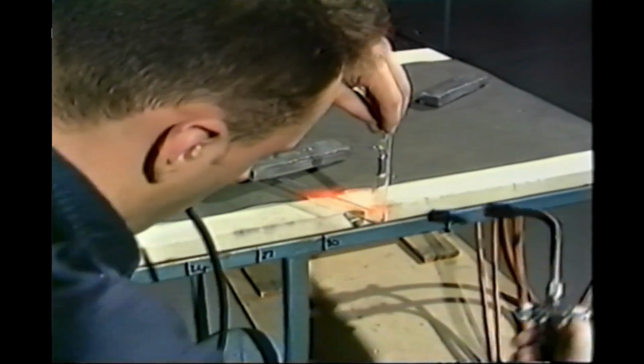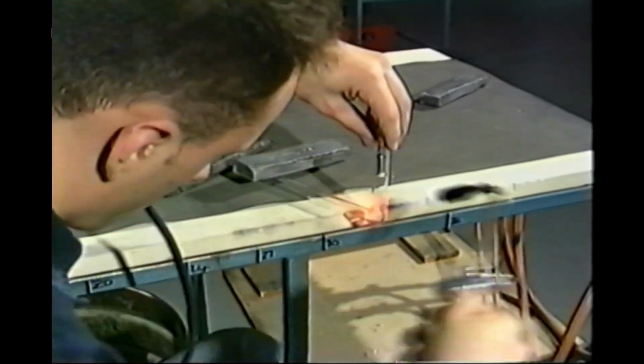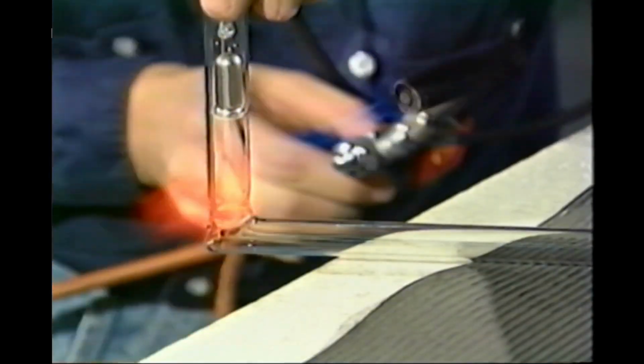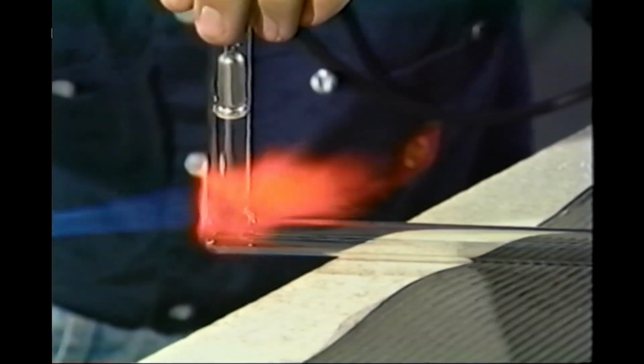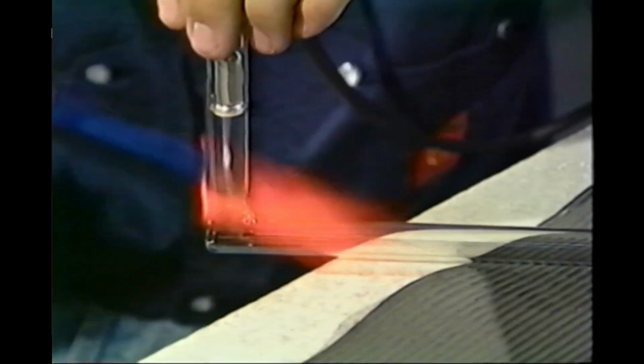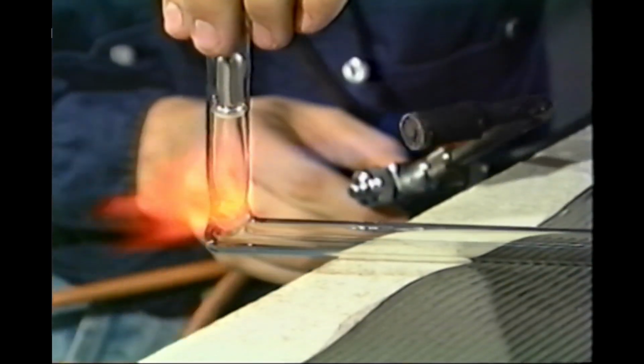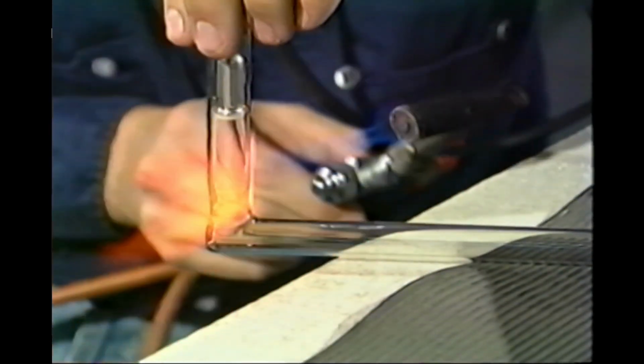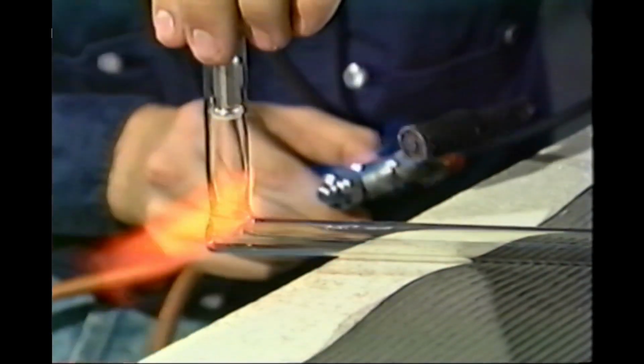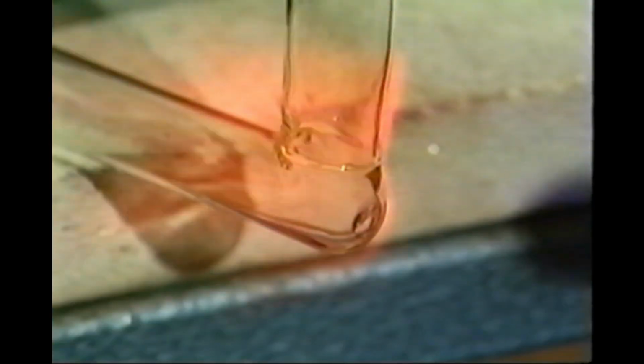Angle the flame down slightly and melt with complete rotations around the electrode from the joint line up. As with the electrode joint, do not allow the electrode to move up or down during melting. When the area being melted reaches a bright red heat, cease rotating the flame and direct it at the area which will become the outside radius of the bend, and melt this area longer.